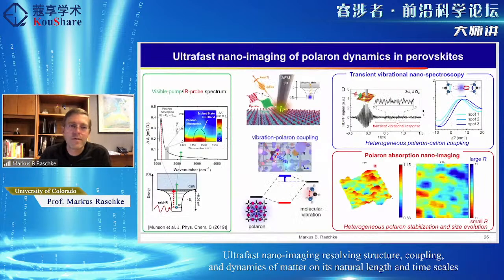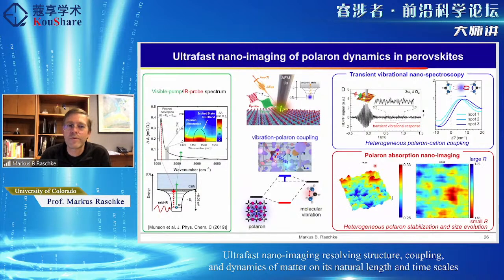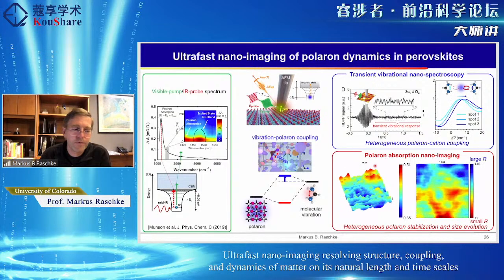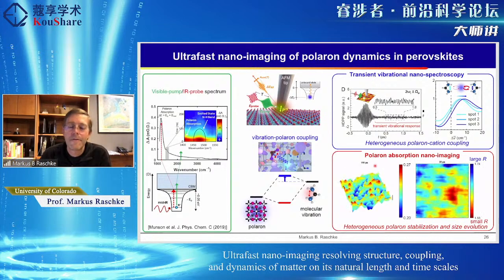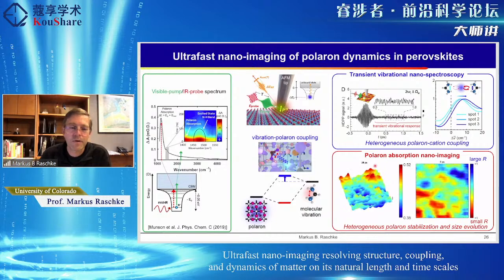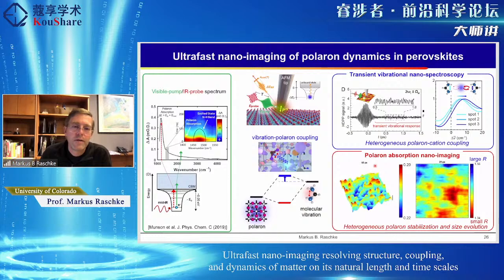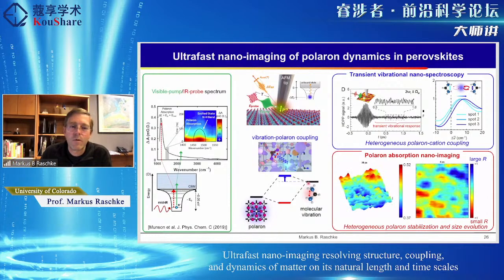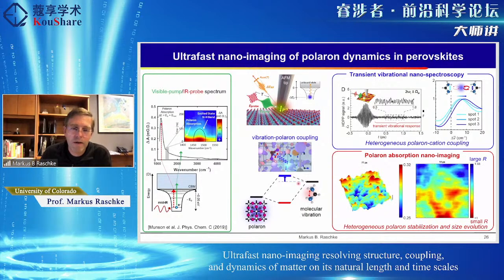So with this, I'd like to summarize this part, where I showed you how, by far from equilibrium excited state dynamics and ultrafast nano-imaging, we were able to unravel some of these difficult to handle or difficult to optimize elementary processes at work in perovskites. This is both probing the molecular vibration as a local sensor of the local chemical environment on the lattice scale, and then the coupled polaron evolution and stabilization dynamics of these carriers as they evolve.